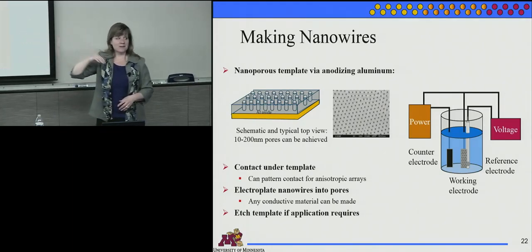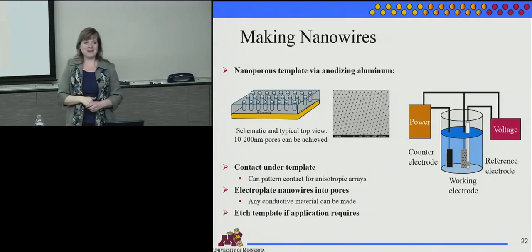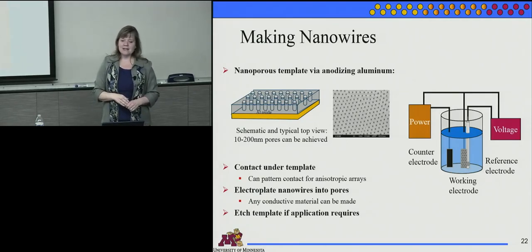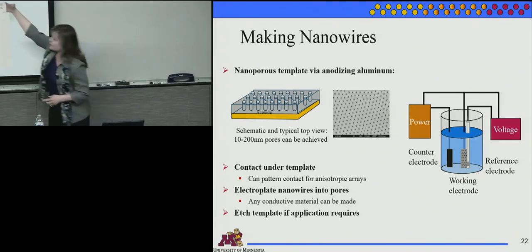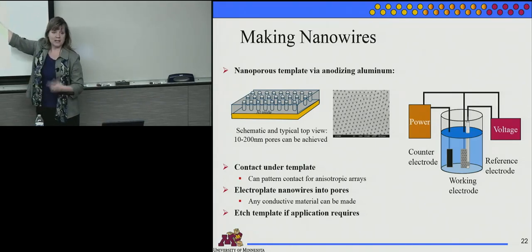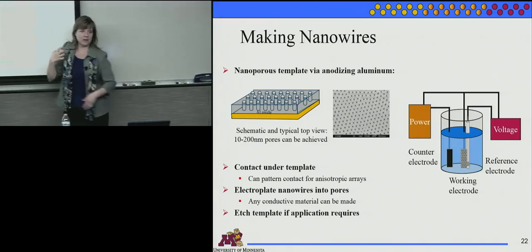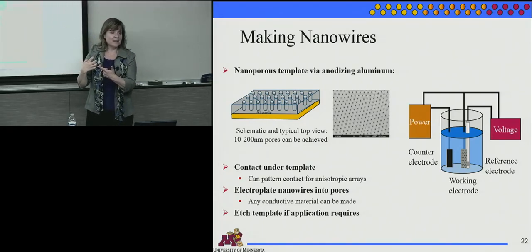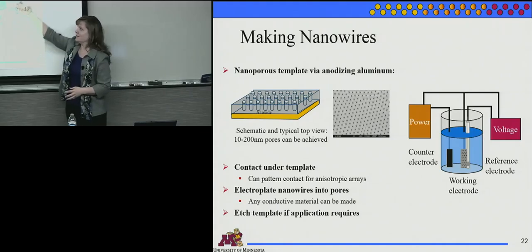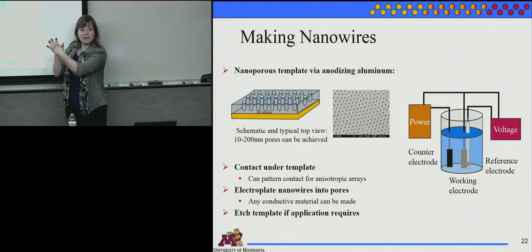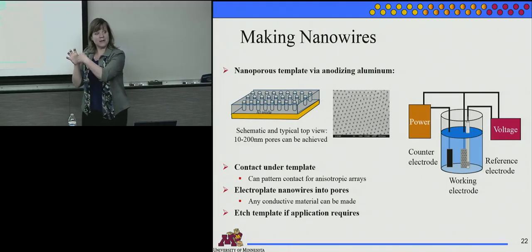Now I had a student, since you're all students, I can tell you this. I don't always share this story because it's a little weird, but he tried every polymer he could find and everything that he could then dip into this bath. You need the back to be protected from the electrolyte, or you're just going to grow a film on your copper there, right? So he was protecting it, dipping it in, trying to make sure that the only place the electrolyte saw contact was down inside the pore.